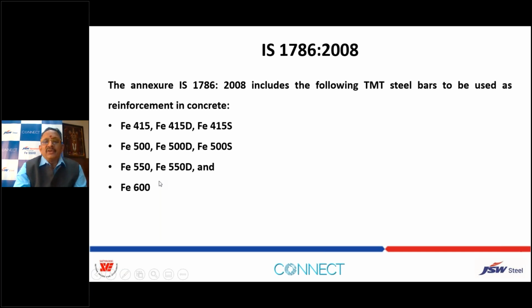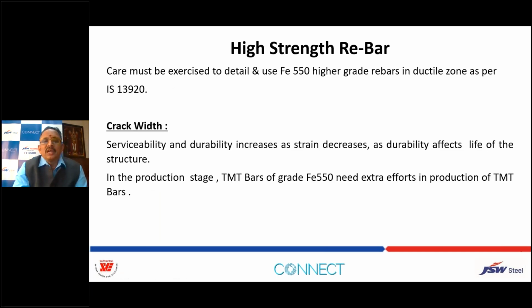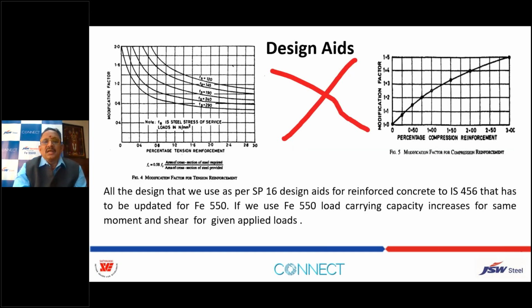And the crack width calculations we have to do when we are using this higher grade reinforcement because of the higher stresses. Though we are increasing the strength of the steel, the concrete we might be using M25 or M20 or highest M40, M50 also. So it's always good to check the crack width as per our tensile stress in the rebars.